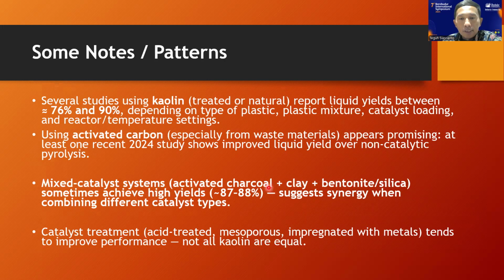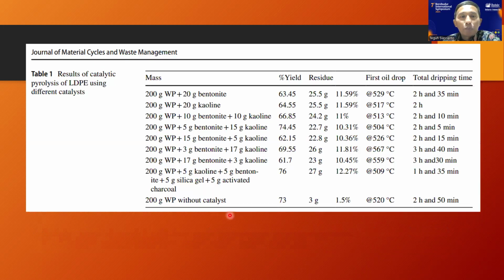Activated charcoal, clay, and silica sometimes achieve a high yield of about 87%, which suggests synergy when combining different catalyst types. And also catalyst treatment, such as mesoporous structures impregnated with metal, can improve kaolin so it can make a better zeolite. This is the special paper that we want to compare, because it uses different catalysts from clays: bentonite, kaolin, silica gel, and the most important, they are also using activated charcoal as a catalyst.